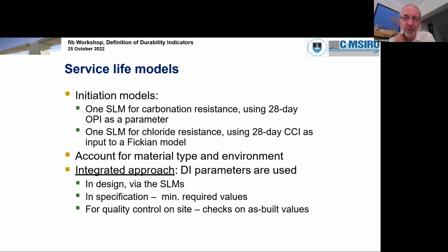These models account for material type and environment, importantly, and it's an integrated approach, or this kind of closed loop. We use it in design via the service life models, in specification, in which minimum required values are given, with the number of defectives that are allowed and so on, and then for quality control, checks on the as-built values, and in this case, there are also penalties that are built in for not meeting these values. So the contractor would have to pay penalties if the values are not met.